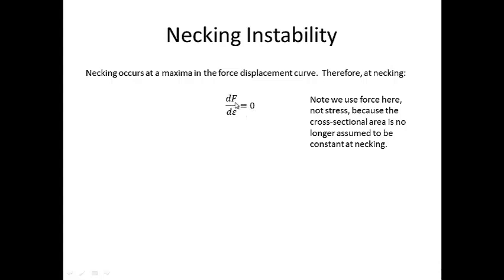Now keep in mind here that we're not using stress in this equation, which would make more sense maybe intuitively, but the reason we don't use stress is because the assumption behind stress is that there's a constant cross-sectional area, and we can't make that assumption once necking occurs, so we have to use the force instead of stress. But nonetheless, we assume that the change in force with respect to strain is equal to 0 at this yield point where the necking occurs.